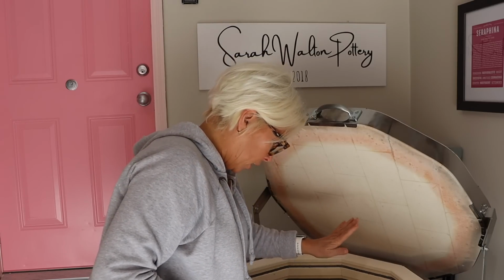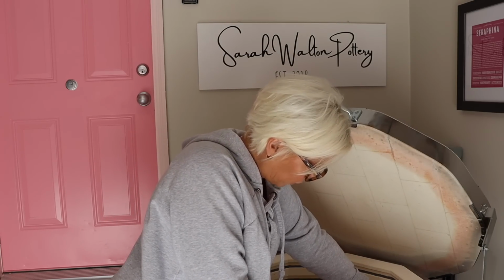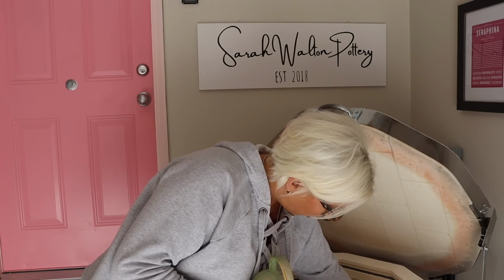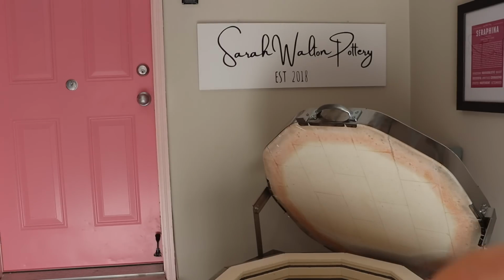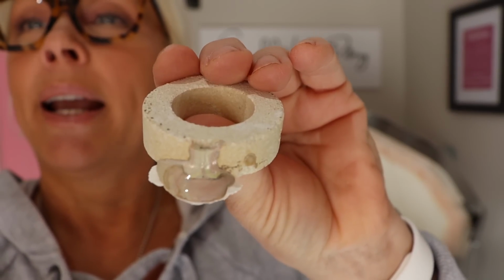This is a refire. Two things are refires here. Oh, that one fused. Oh, okay, that's easy. It did. It ran off onto my cookie. I'd added new kiln wash before I did this firing, and you can see it ran. And I have not thrown any of my raised cookies, so I desperately need to do that. And so this is a refire, and as you can see, refires don't always work. I ended up getting pinholes on this one.